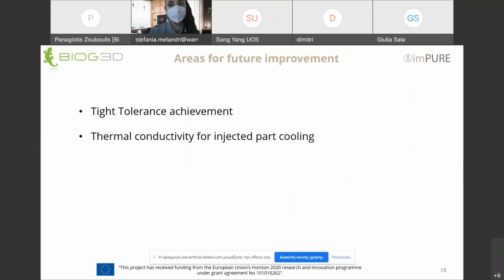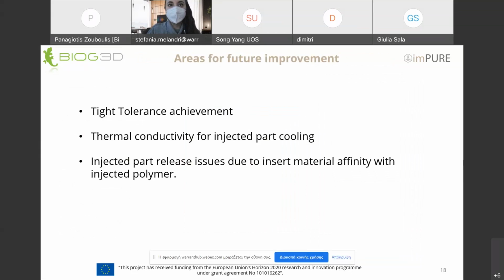Some areas for future improvement that are also the challenges that we encountered. It's achieving tight tolerances for the assembly of the mold, the thermal conductivity of the mold material that is required for cooling of the injected part, the potential release issues of the injected component due to the affinity that the polymer might have with the mold insert, and the durability of the insert itself that prevents its use for long-run production.